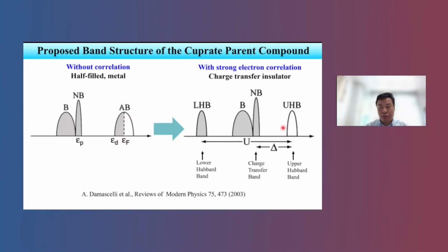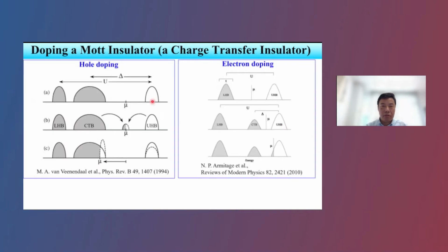Then the question is, if you dope it, how do you produce low-energy states? If you have a parent compound, the chemical potential is located within the gap. If you dope the system with holes, there are two ways. Either like a conventional insulator or semiconductor, the chemical potential jumps into the valence band, or the chemical potential can be pinned and you form new states within the gap. These are the two pictures here. Basically, electron doping is the same picture, but either you form new states in the upper band or within the gap to form in-gap states.